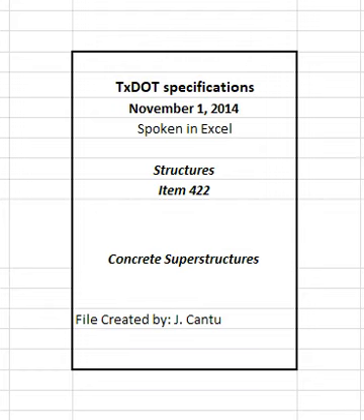4.6.8 Handling and placing. Minimize segregation of the concrete and displacement of the reinforcement when handling and placing concrete. Produce a uniform, dense, compact mass. Do not allow concrete to free fall more than 5 feet. Remove any hardened concrete splatter ahead of the plastic concrete. Fill each part of the forms by depositing concrete as near its final position as possible. Do not deposit large quantities at one point and run or work the concrete along the forms. Avoid cold joints in a monolithic placement. Sequence successive layers or adjacent portions of concrete so they can be vibrated into a homogeneous mass with the previously placed concrete before it sets.